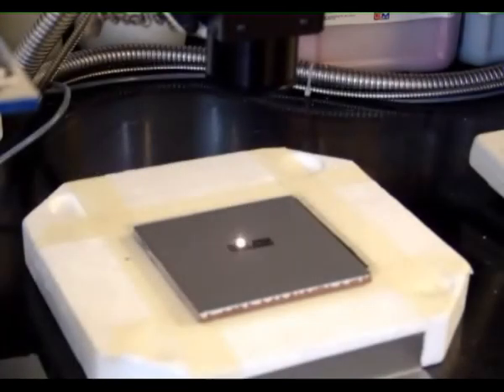After allowing the material to dry completely, you can begin laser marking. Marking settings for the LMC series are different than for our metal marking products. On a 35 watt CO2, a recommended starting point would be 50% power and 25% speed on ceramics.